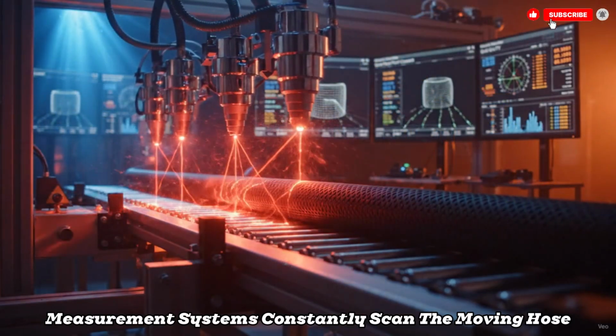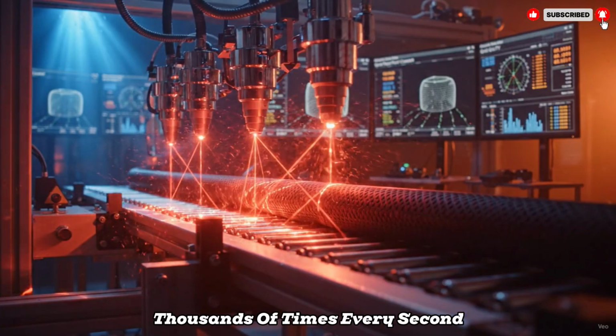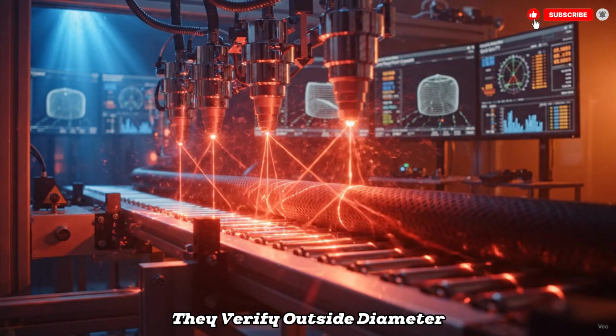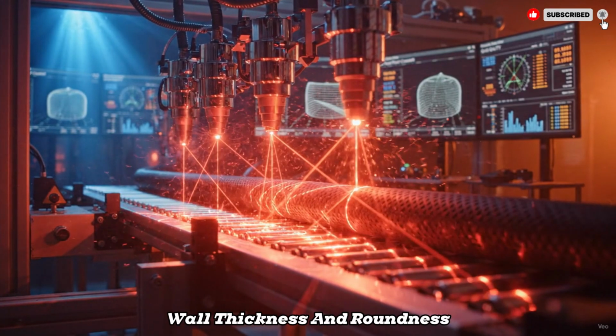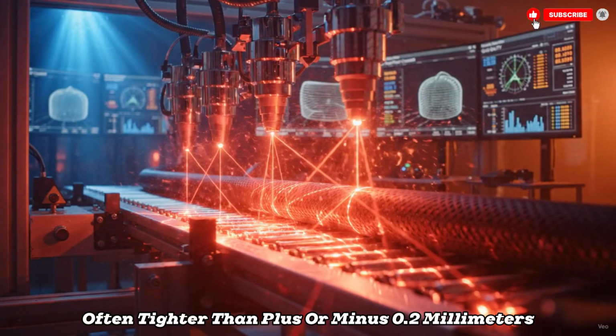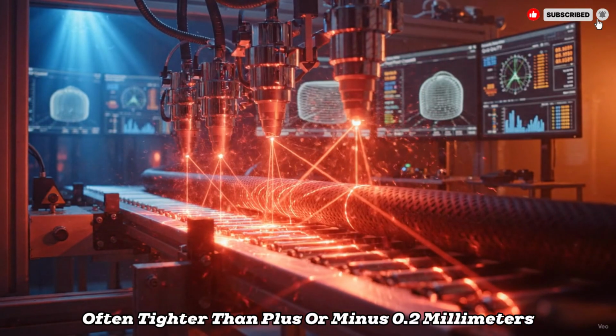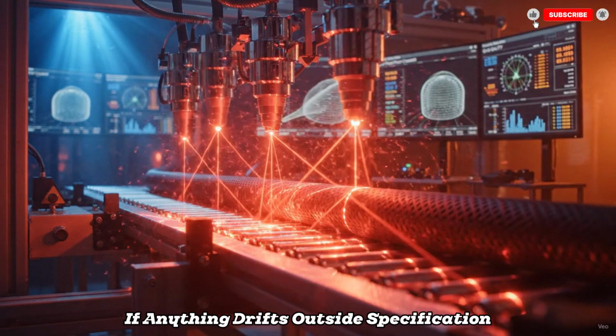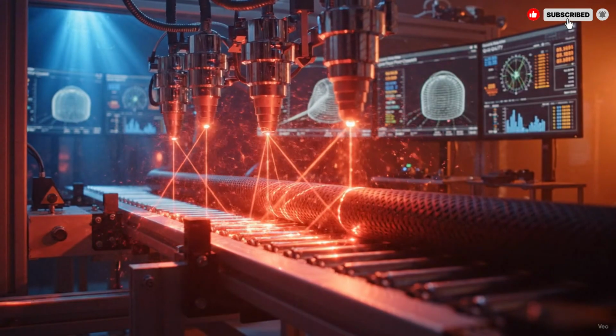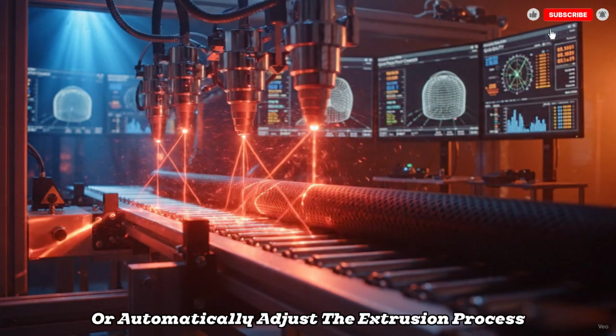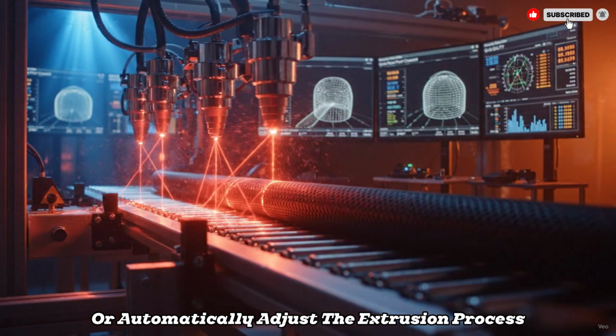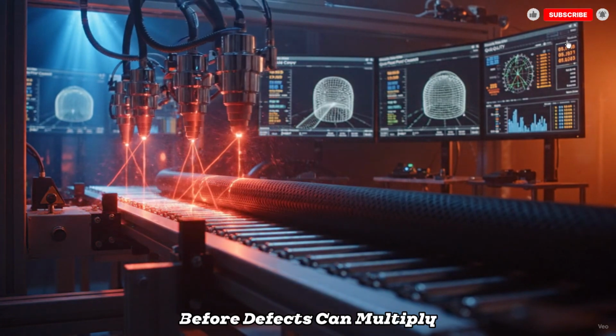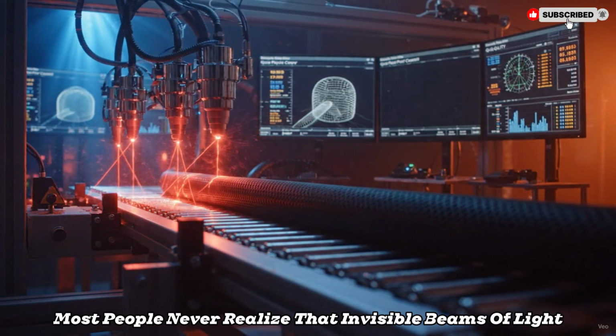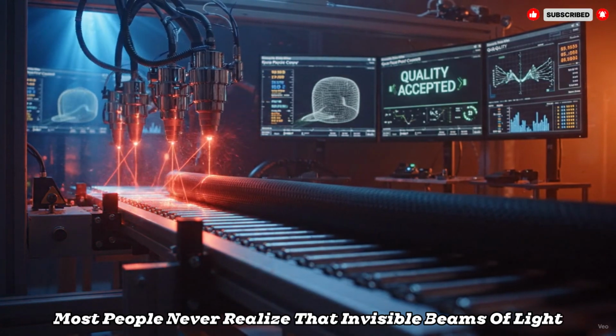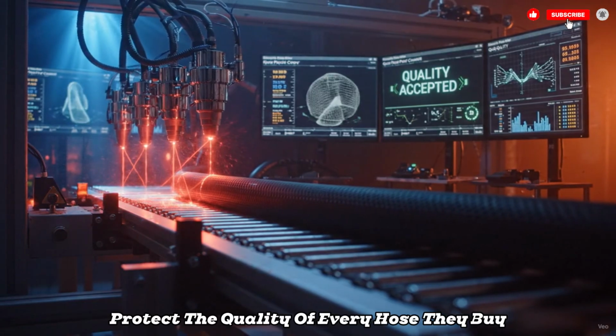Laser measurement systems constantly scan the moving hose thousands of times every second. They verify outside diameter, wall thickness, and roundness with tolerances often tighter than plus or minus 0.2 millimeters. If anything drifts outside specification, computers instantly alert operators or automatically adjust the extrusion process before defects can multiply. Most people never realize that invisible beams of light protect the quality of every hose they buy.